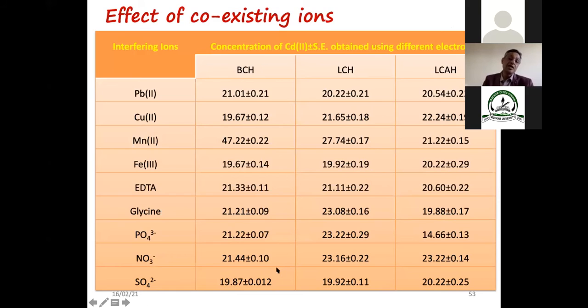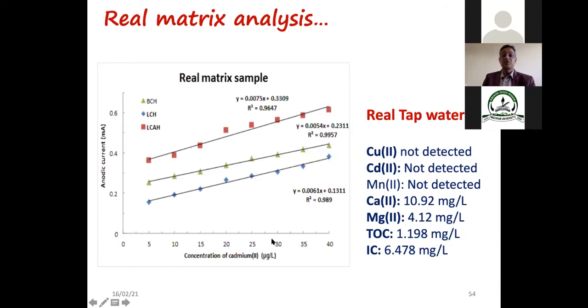These are some of the data that we obtained for the different materials, and how other ions are interfering. We tried to see whether coexisting ions interfere or not. In this case, most of the ions are not affecting, but in the case of manganese, a very high signal was observed. That is maybe because manganese is also getting reduced or oxidized at almost the same potential, so it is going to interfere. This we also tried in the real matrix sample, and again we obtained very good linearity and correlation.